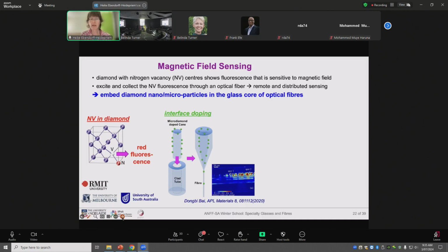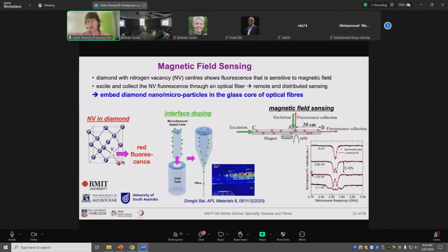To get the nanoparticles or microparticles into a fiber, to use a fiber for the sensing, for example for remote sensing applications, we took a thin glass rod, dip-coated it with diamond particles, and placed it into a glass tube. This assembly was drawn down to fiber, and you can see here this is the fiber, in which we have embedded the particles so that they are now fixed in the fiber, a robust piece. This is a method to embed the particles in a fiber itself, which then can be used for the sensing, and I won't go into details how the magnetic field sensing is done.